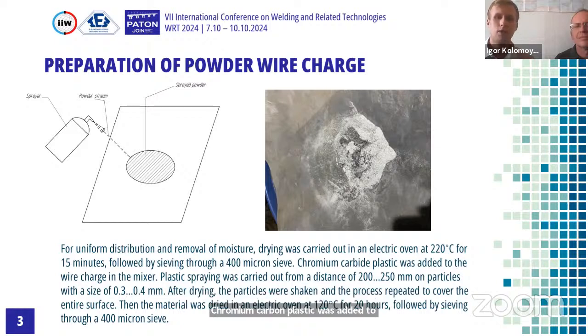Plastic spraying was carried out from a distance of 200 to 250 millimeters on particles with a size of 0.3 to 0.4. After drying, the particles were shaken and the process repeated to cover the entire surface. Then the material was dried in an electric oven at 120 degrees Celsius for 20 hours, followed by sieving through a 400 micron sieve.